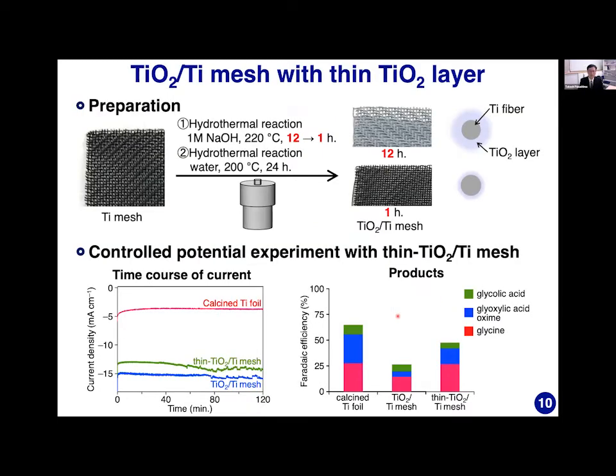We thought that titanium metal covered with a thin titanium oxide layer is a key structure. Thus, we prepared a titanium oxide titanium mesh with a thin titanium oxide layer using a hydrothermal reaction with shortened reaction time. Then we tested the performance of the newly prepared electrode for glycine electrosynthesis.